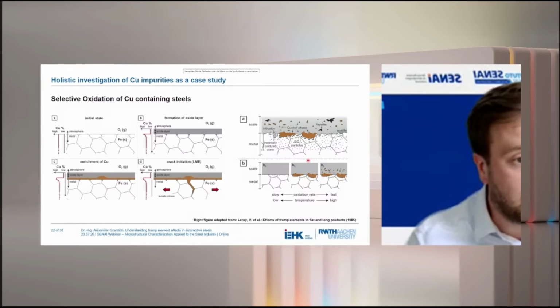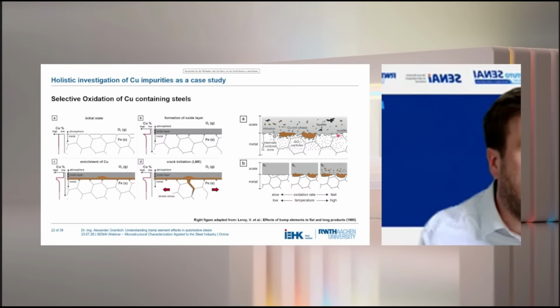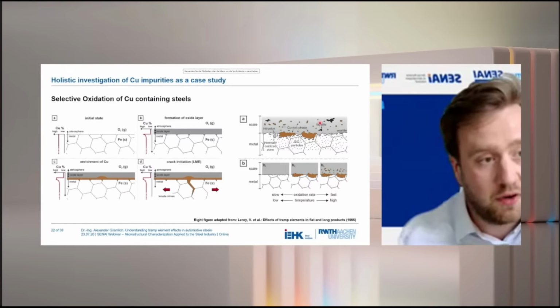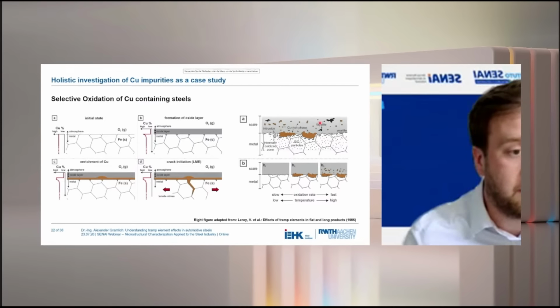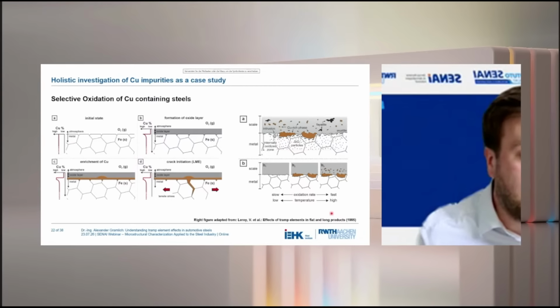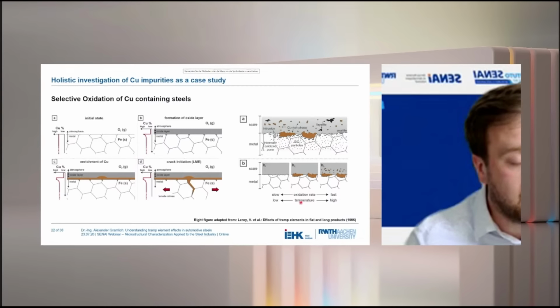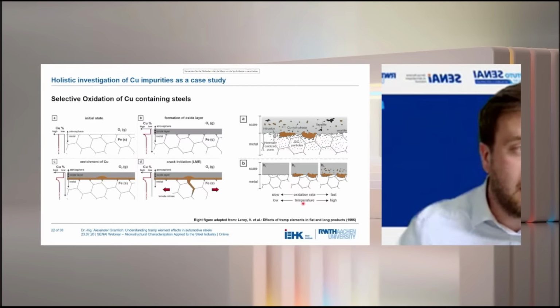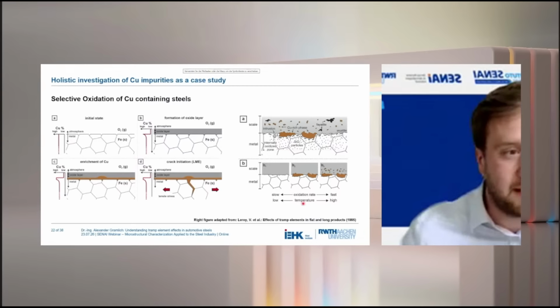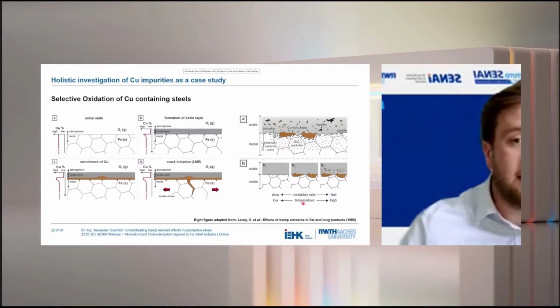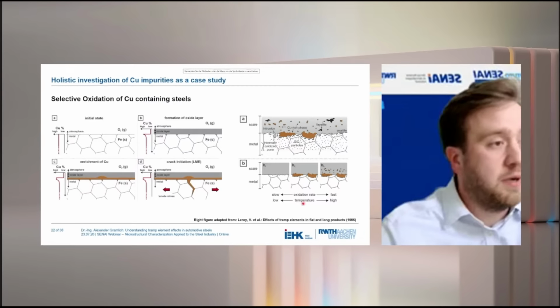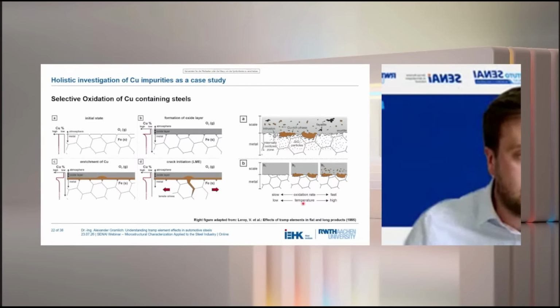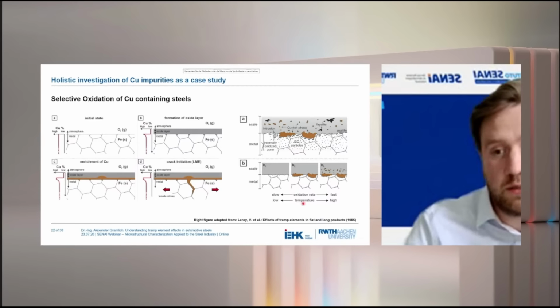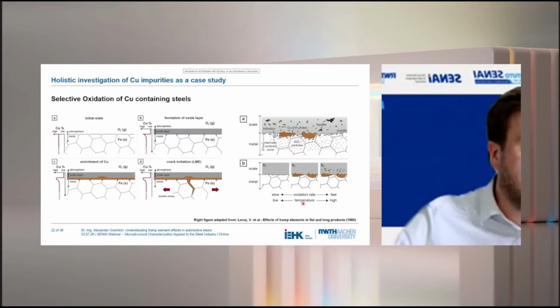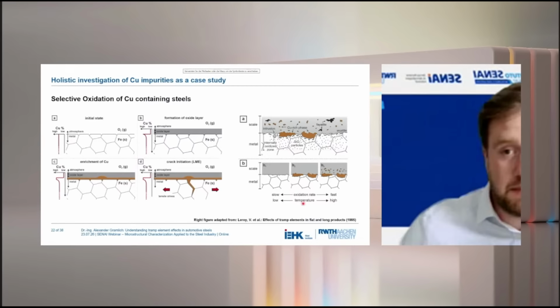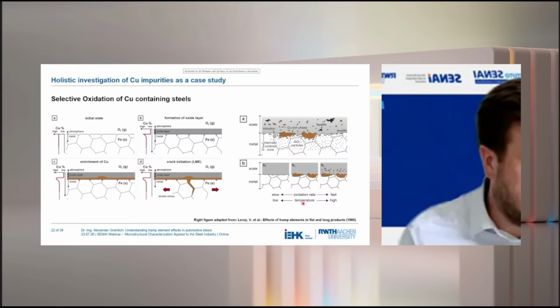This can be influenced, of course, either by working with other scale influencing elements like silicon, for example, or by working on the process parameters like the oxidation rate or the temperature. By this, you can push the copper a bit into the scale layer. However, it's still an issue which is not, let's say, completely understood. Some ways exist for working around it, but these ways are often defined only for a single steel, and the mechanism behind it is still under investigation.